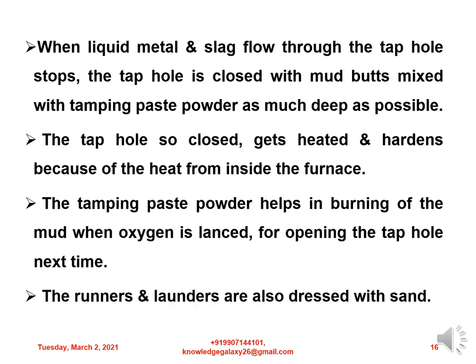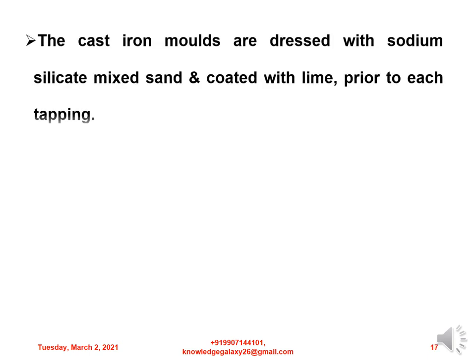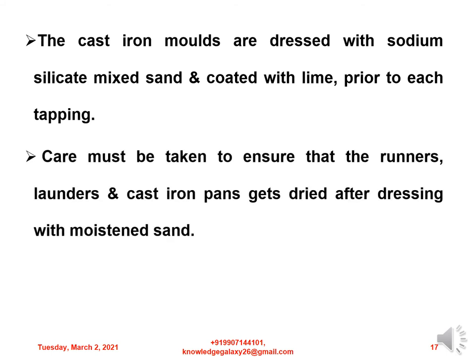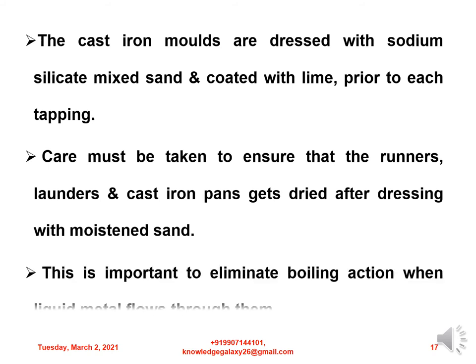The runners and launder are also dressed with sand. The cast iron molds are dressed with sodium silicate-mixed sand and coated with lime prior to each tapping. Care must be taken to ensure that the runners, launder and cast iron pans get dried after dressing with moistened sand. This is important to eliminate boiling action when liquid metal flows through them.